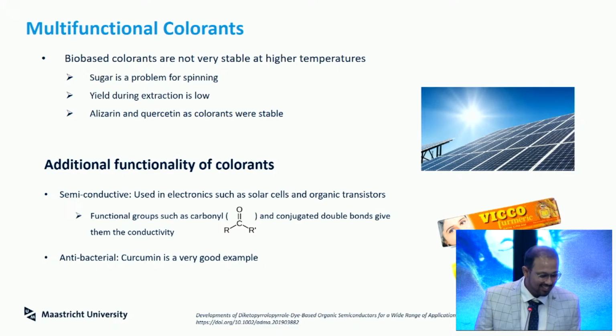And then I thought, okay, if I'm going to work with colorants, why don't I see what else it can be used for apart from just coloring? The other part of colorants is that if you look at pigments like carbon black, it's one of the commonly used black pigments, which is also conductive and used for anti-static fabrics. So this was the second functionality I learned. And if you look at the chemical structure of the colorants, you always have functional groups, which meant they could also be more conductive than the polymer I'm using. That's what we wanted to look into.